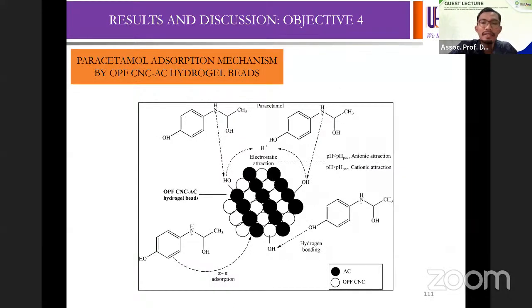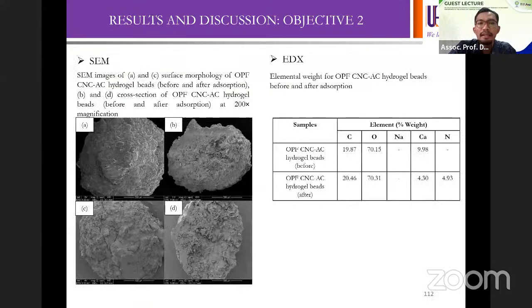So the mechanism that we have proposed is that the electrostatic interaction could happen on the surface of the beads, interacting with the wastewater, which in this case we use paracetamol as the wastewater from the pharmaceutical industries. And the characterization of the beads after adsorption also shows the presence of paracetamol residues, which means that the waste has actually been adsorbed on the surface of the beads.